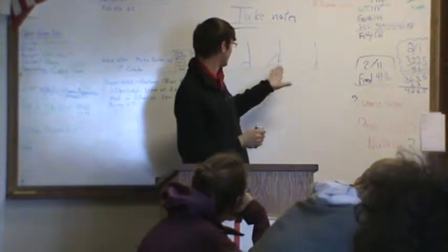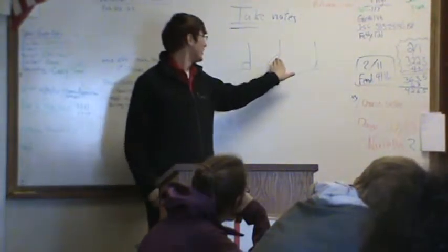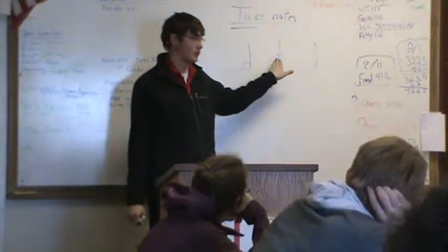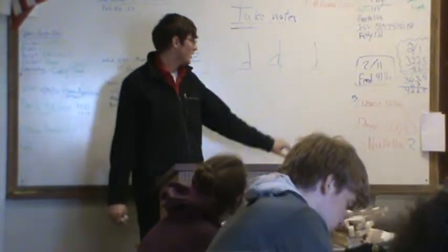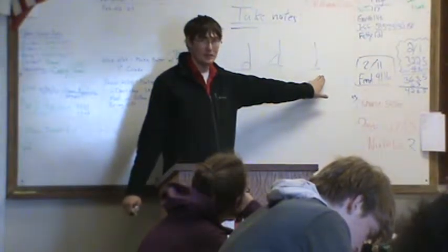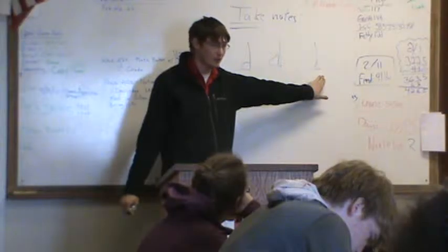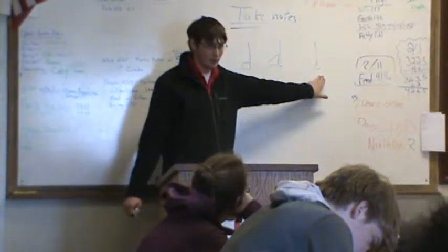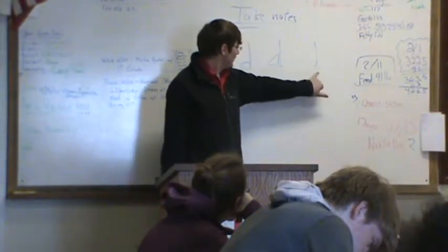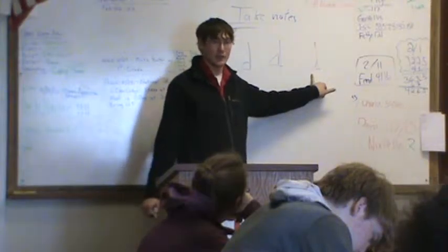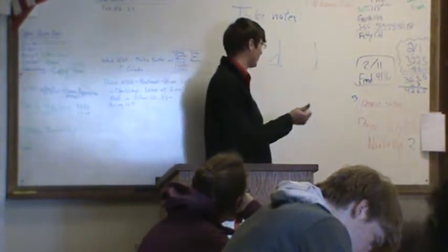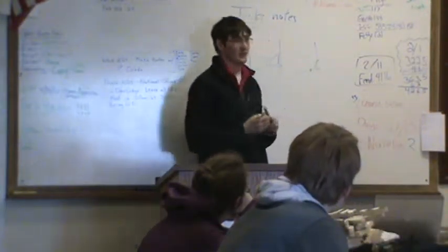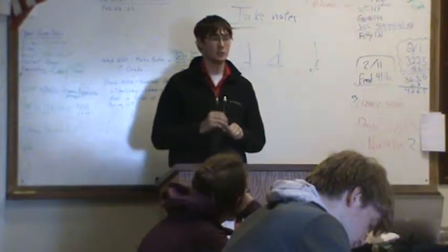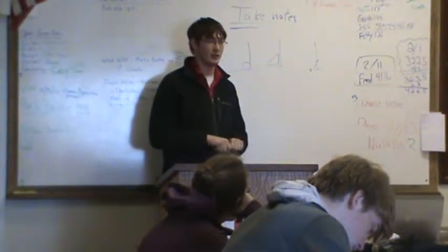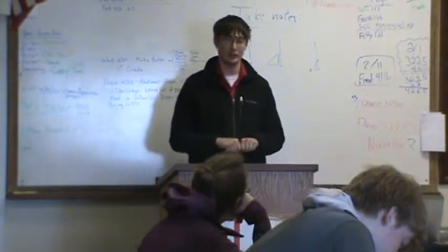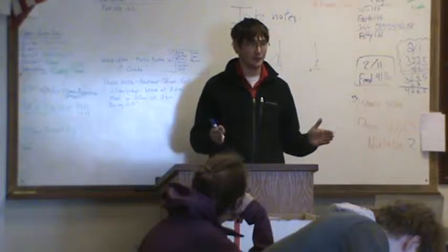Typically we'll want to see something that looks fairly flat on top. That indicates you have pretty good fusion, and you have adequate filler material being deposited into the weld. If we see a concave weld, that means you're either running too hot or you have too little filler material between your weld plates. And if a weld's too hot, you oftentimes run into areas where you're going to have brittleness on the edges of your weld, which is exactly where your weld's going to fail. Because the weld should be the strongest point of your conjoined materials. And when a weld fails, it usually fails on the edges of the weld, especially if you get it too hot.